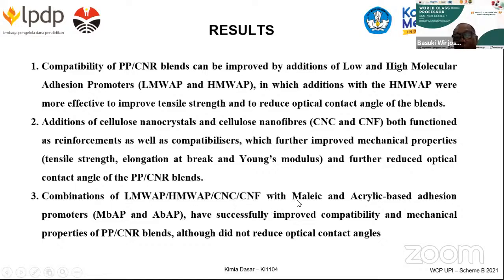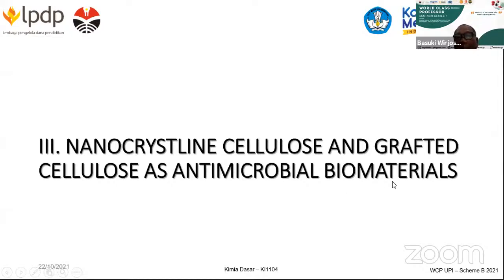And then this is what we produced: maleic and acrylic based adhesion promoters. We introduced them to the blends as a substitute for the commercial high and low molecular weight adhesion promoters. We also got improved compatibility, but the contact angles did not reduce. Why? Because maybe there are free maleic or acrylic groups, which are very hydrophilic, so the contact angle doesn't change substantially.